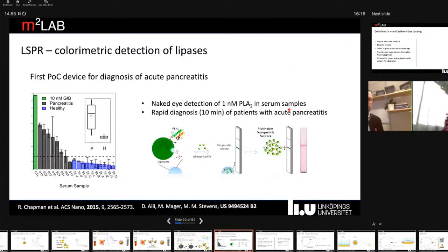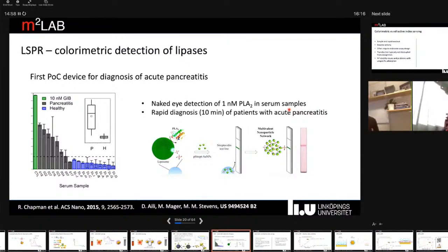And this was then later also developed further, together with collaborators, into a device for diagnostics of pancreatitis, where you have quite a large overexpression of lipases. And this is an acute pathological condition which requires immediate attention by a physician, or you need care within hours, essentially. So a rapid diagnostic here is key for the correct treatment. And with this lateral flow device based on this concept, it was possible to diagnose pancreatitis in patients in serum samples within 10 minutes.